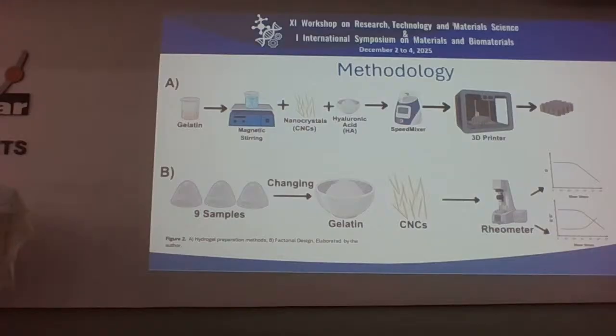But there is a problem, because not every hydrogel results in a printable material. Therefore, to identify the formulation, I carried out a factorial design with 9 different samples, varying the concentrations of the nanocrystals and gelatin, to analyze the elastic modulus and the crossover point between the moduli, called the gel point, using a rheometer.